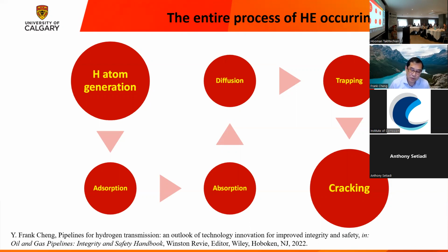Okay, after hydrogen atom goes into the metal, it can diffuse in the crystal lattice of the metals, of the steels. And if the hydrogen diffuses randomly in the metal, usually it can make the hydrogen distribution uniform. So we don't worry too much. However, there are so many different defects existing in the metals, and they can cause local trapping of hydrogen. So step number 5 is the trapping of hydrogen atom. If the trapped hydrogen reaches a certain concentration, combined with a certain metallurgical microstructure and mechanical stress, then cracks can be initiated. That's called hydrogen-induced cracking. So basically, there are 6 steps included in the entire process.